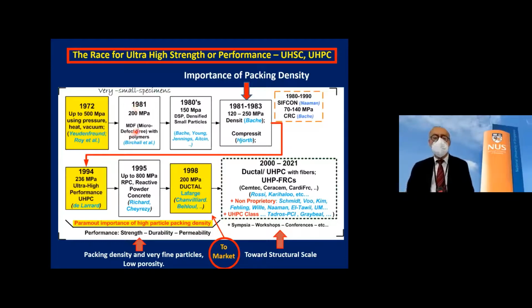In 1981, a study by Birchell et al. came out from the UK on what they called micro defect free cement. That was my time already. I'm interested in everything that is going on. And we were excited when they said they had 200 megapascal, until we found out that they used polymer in addition to the cement, and they had some other curing and heating procedures. So it was a very specialized product, but it was not completely cement. If half of it is polymer, it's not exactly cement.